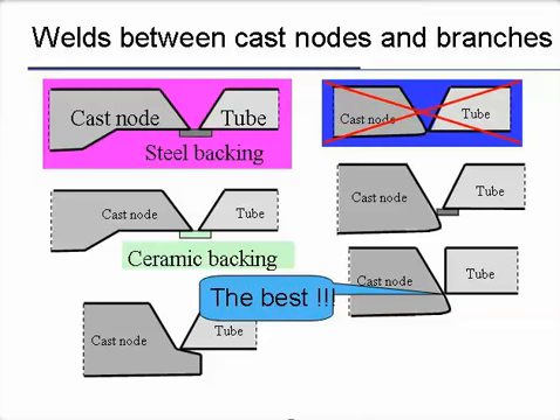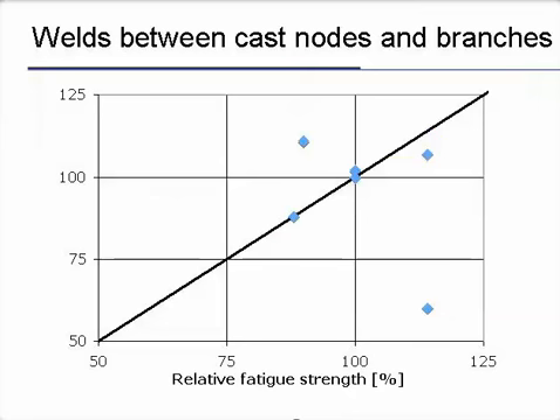You have different solutions. We have tried different ones. Effectively, to have some backing here so that you can effectively compensate for the tolerances, or try to make it here directly, but with a certain angle here, so it does kind of a sort of backing, but not very good. So we said maybe we need to do the end of the cast node like this, which is common, but then again, you have maybe some problem of tolerance in the other direction. So this is the different solutions. Well, guess what? The best is this one in fatigue. The simplest is the best.